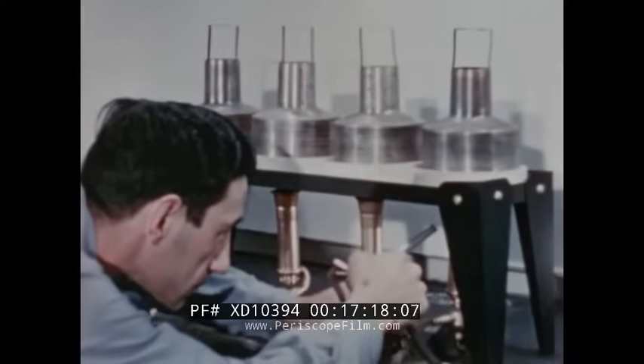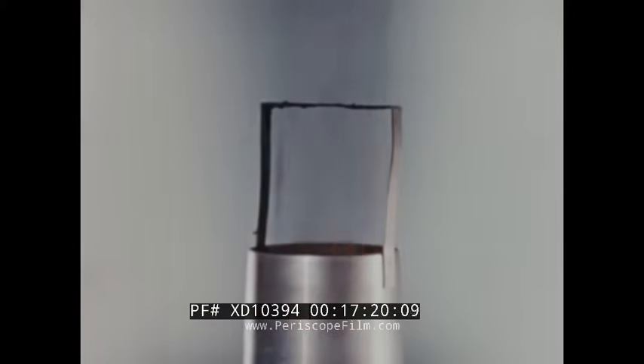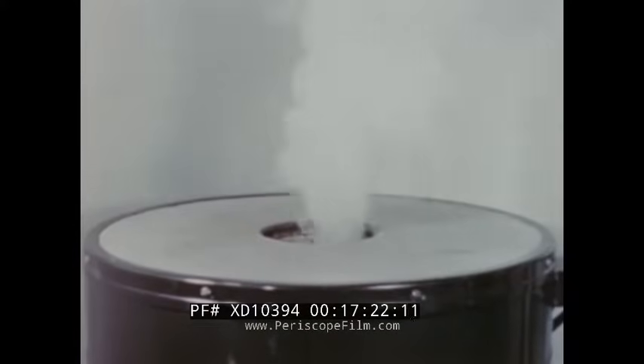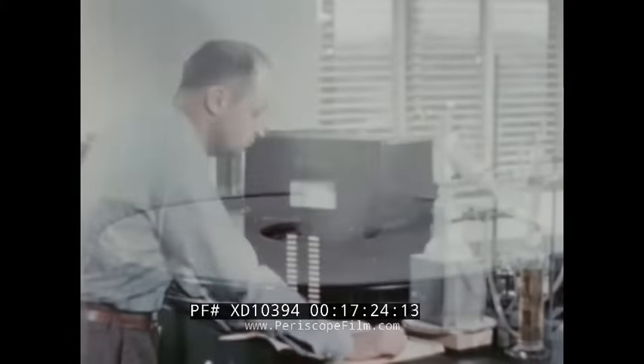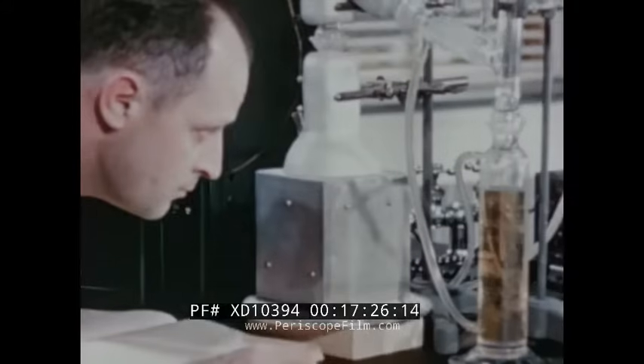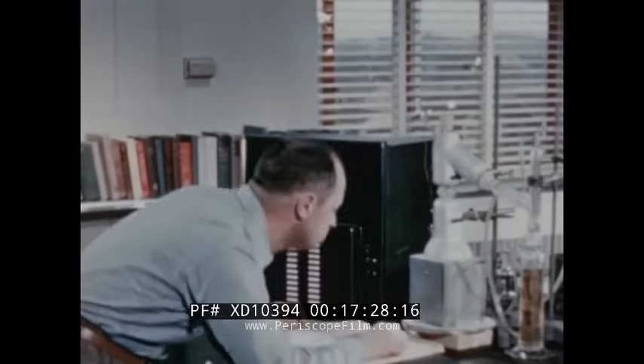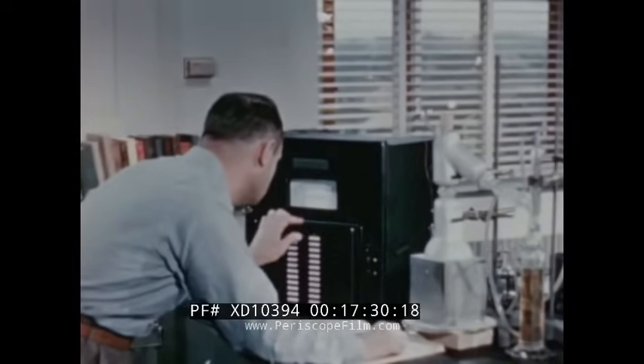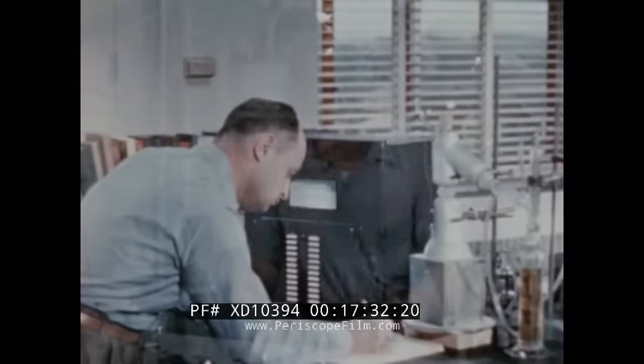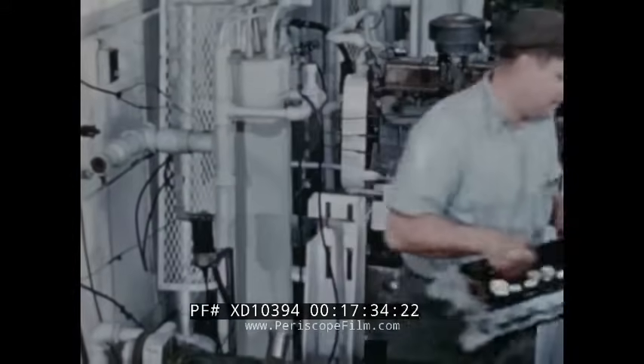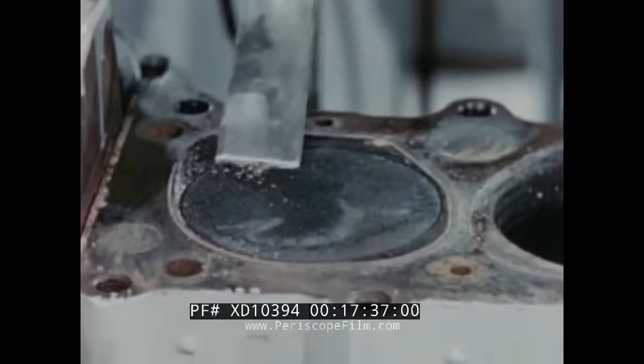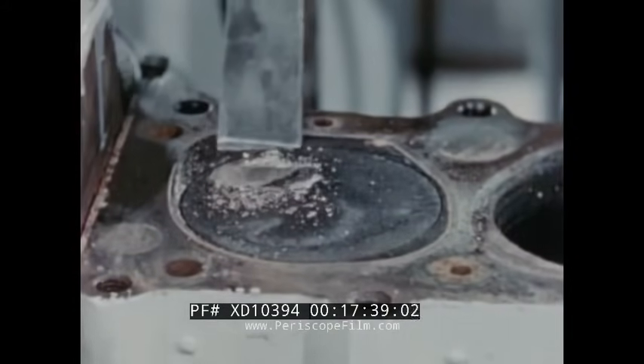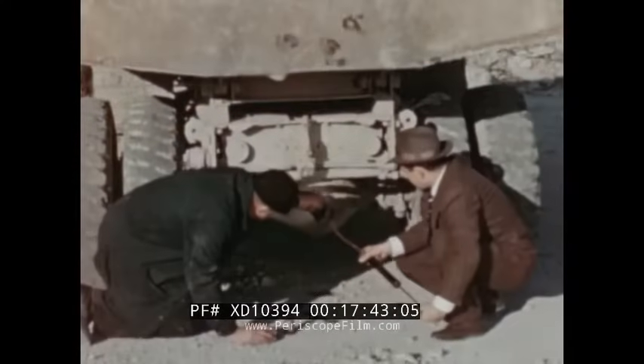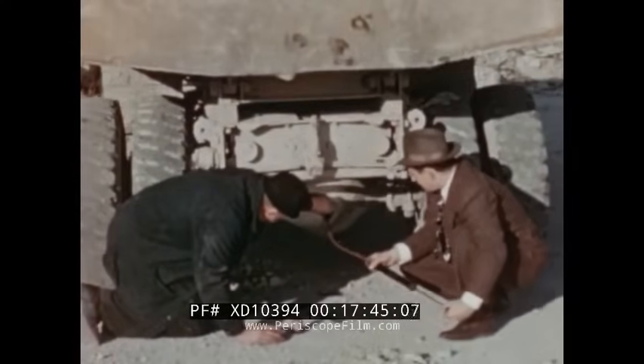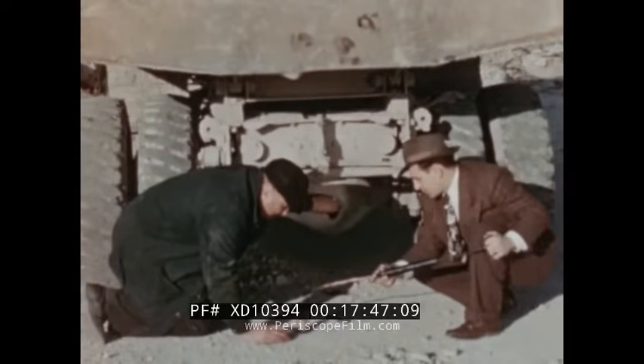Tendency to form carbon is shown by this carbon residue test, or by this more modern Ramsbottom method. An excellent check on carbon forming tendency is obtained by distilling the oil under a high vacuum and collecting and measuring the combustion residue. Formation in the engine is, of course, the ultimate test. Service in the field is, after all, the best way to prove the practical worth of a product.